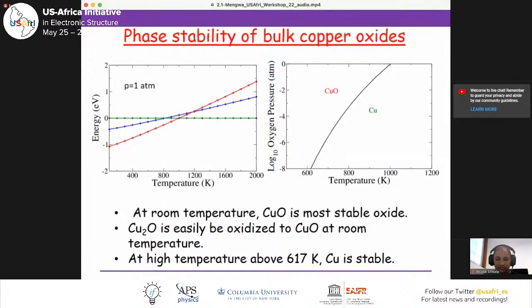The first is the stability of copper oxides. Now, when ab initio molecular dynamics calculations are carried out, it's found that at room temperature, CuO is the most stable oxide. Cu2O is easily oxidized to CuO at room temperature. At high temperature, above 617 kelvins, copper is actually the most stable.